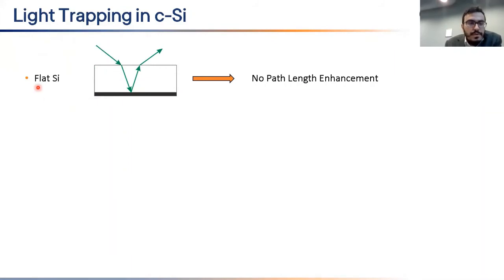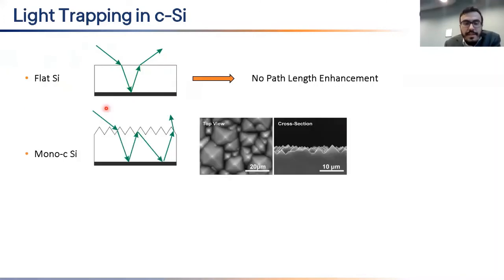When you have a flat silicon surface, light enters your silicon wafer, travels a minimum distance inside your cell, and escapes. However, when you have some texture on the surface of your wafers, you can have this light traveling more distance inside your solar cell, so absorption probability is increased. Therefore, you get more efficiency from your solar cell, and you can see the surface of an industrial monocrystalline silicon solar cell, where you have micron-sized micropyramids on the surface that enhance this light trapping.